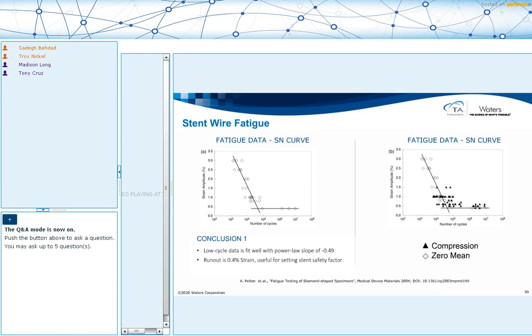What we see in this slide is that in the low cycle portion of the fatigue data, they were able to do a power law fit with a slope of minus 0.49. So this helps them create a model to understand the behavior in that region of the graph better. And then below 0.4% strain, the stent wires, the surrogate sample, did not break. So this shows us that we have a certain strain that establishes a safety factor for designing these stents.